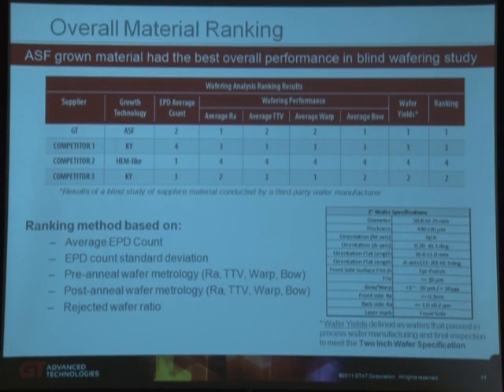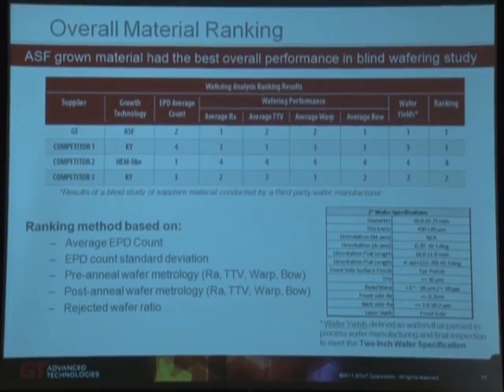If you combined these 3 criteria that we measured, meaning the EPD average count, the wafer analysis ranking results after the annealing process, and the final wafer yields, and you rank those, you see that the GT ASF ranked number 1 as far as the criteria and metrics that matter to the wafering operation.